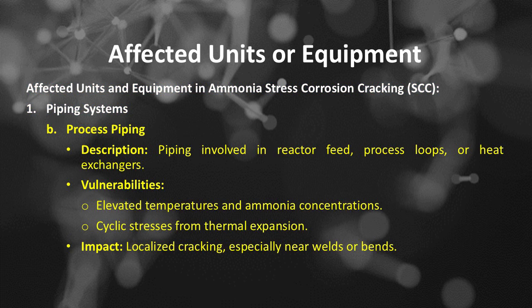Number B is process piping. This is the piping involved in reactor feed, process loops, or heat exchangers. The vulnerabilities of this process piping include elevated temperatures and ammonia concentrations, and cyclic stresses from thermal expansion. The impact would be localized cracking, especially near welds or bends.